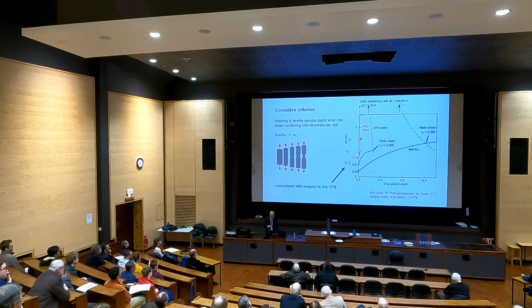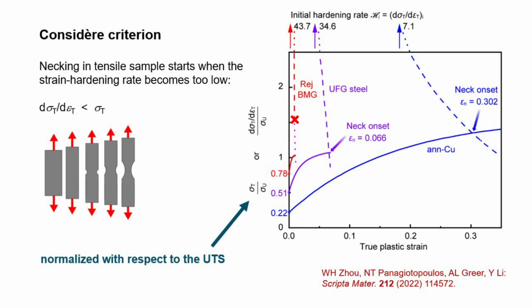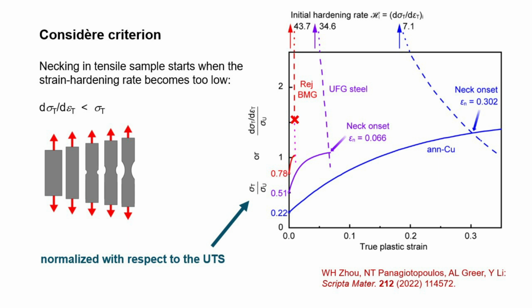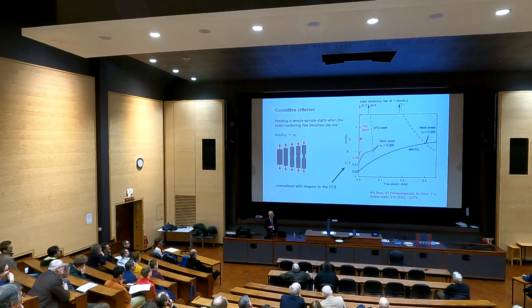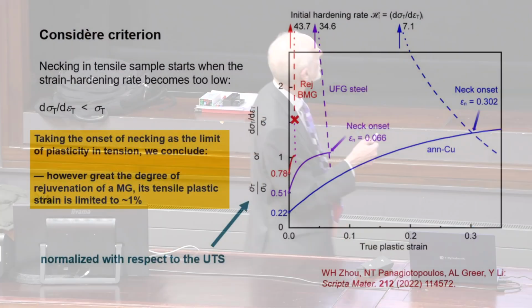I will skip the details of this. Metallurgists in the audience will be familiar with the Considère construction. But it's a way of predicting what is that elongation we could get, the so-called ductility. And I already mentioned that for copper, it's 30%. For our metallic glass, it's at best about 1%, even with the hardening. So we got strain hardening, but there's work to do to make it a more useful strain hardening than we have achieved so far. So we're limited to about 1% ductility.